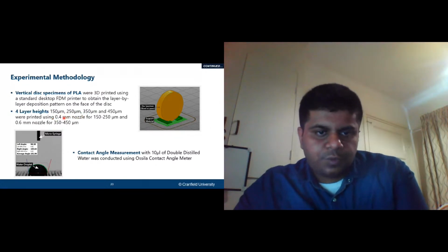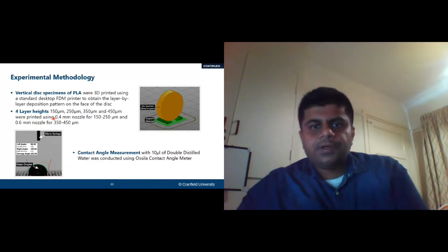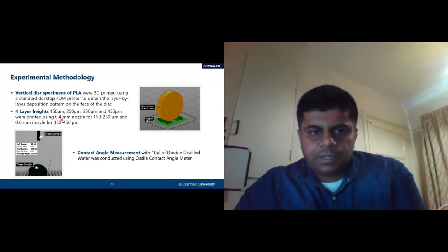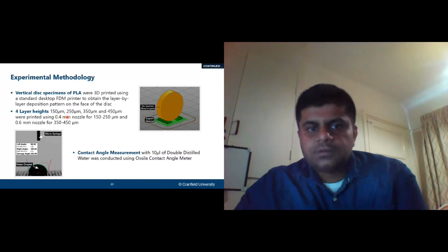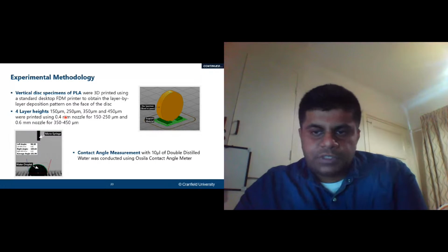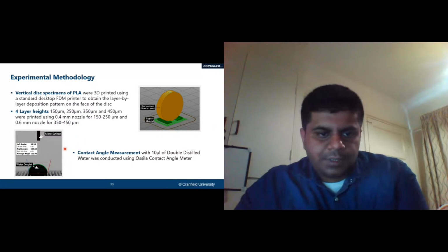And we used 0.4 mm nozzles for these particular layer heights and 0.6 mm nozzle for these particular layer heights. The choice of nozzle was set because if you look at the flow map behind the 3D printing, you cannot actually print a 450 micron or 350 micron surface using a 0.4 mm nozzle, because at the end of the day, the layers will not stick to each other. So you can only use a layer height that is 80% of the nozzle diameter itself. So for this, we had to change the nozzle. This also gave us some good results afterwards. So we're going to discuss that right now.